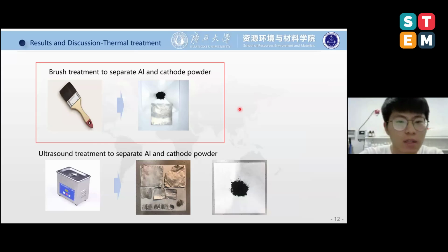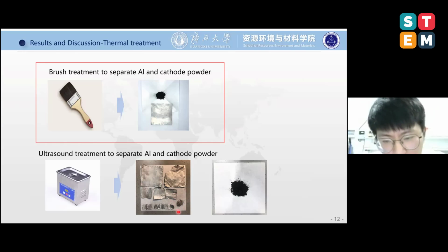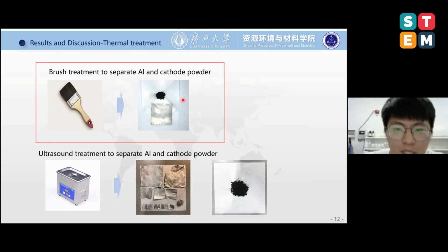And we also investigate how to separate aluminum and cathode powder. We compare brush treatment and ultrasound treatment. Because ultrasound treatment has high energy, it destroys the aluminum foil, and we can see here some small aluminum powder, and there will be impurity with the cathode black powder. But with the brush treatment, the aluminum is not destroyed, it can be separated completely. So we use the brush treatment to separate aluminum and cathode black powder.